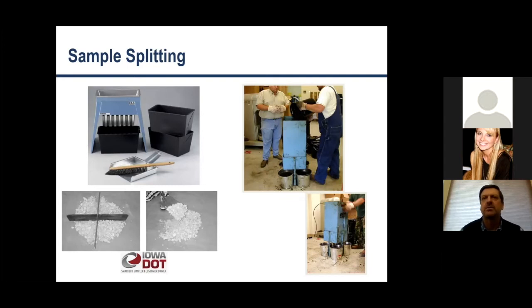Riffle splitters for aggregates are very common. They're used quite a bit for hot mix also. And then spade splitting, like on the bottom left, is fairly common also. And we've got a quartermaster on the right. So it goes back to what the agency requires, right? And being consistent. You don't want one lab using a riffle splitter and the other one using the quartermaster. You want to be consistent, especially if results are going to be compared across those labs.